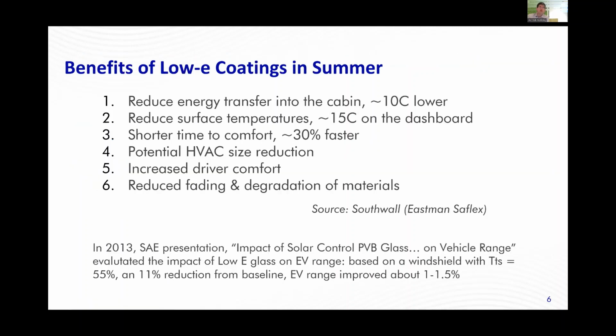And there are a number of benefits of the low-E coatings. In summer, it reduces the energy transfer into the cabin, about 10 C lower. It also reduces surface temperature. You get shorter time to comfort. I grew up in Arizona, and probably the most difficult thing during the day was getting into the hot car late in the afternoon. It takes a while for the air conditioning to bring the cabin temperature down, and then you have all the materials with all that latent heat that's soaked into all the materials. You also have a potential HVAC size reduction, increased driver comfort. Another important aspect too is reduced fading and degradation of materials in the vehicle.